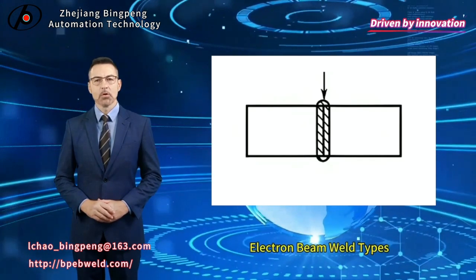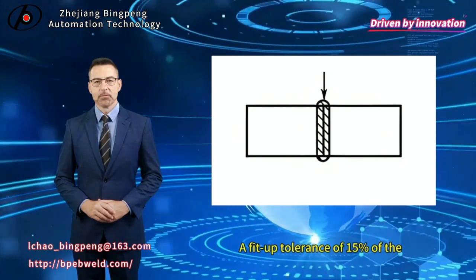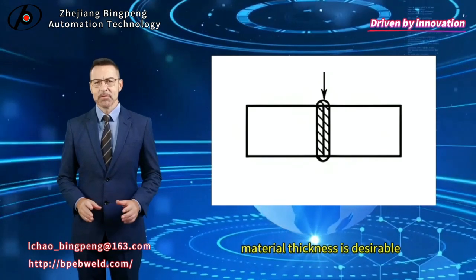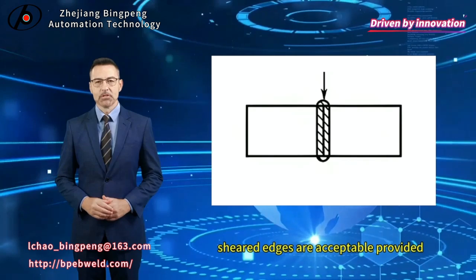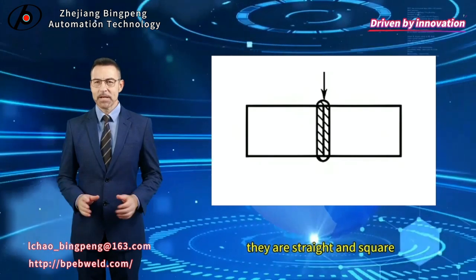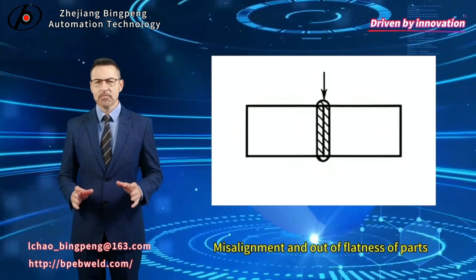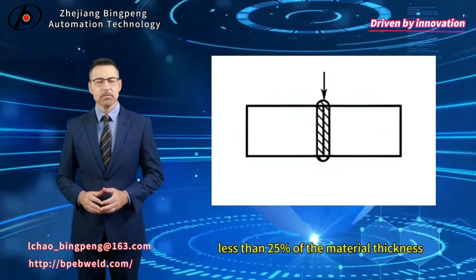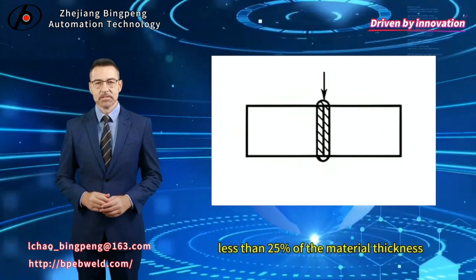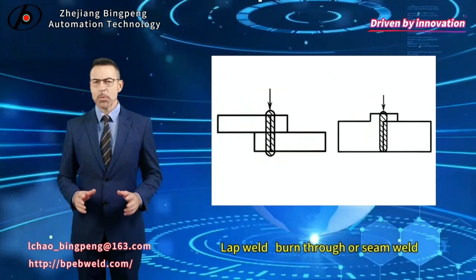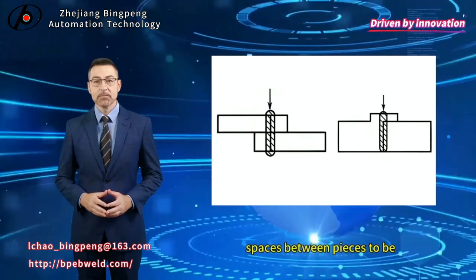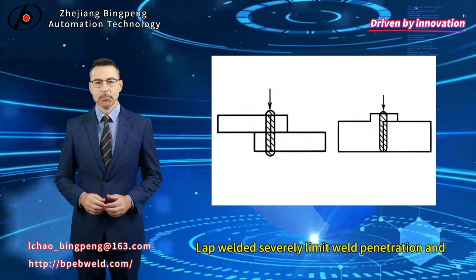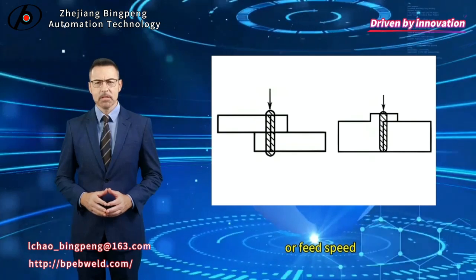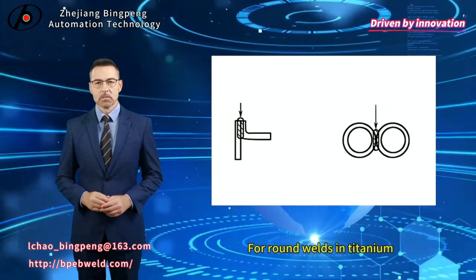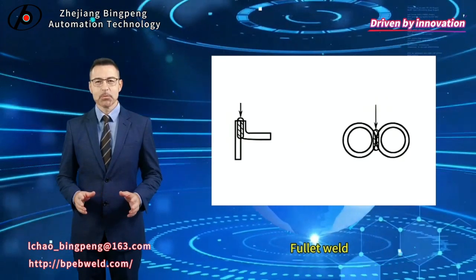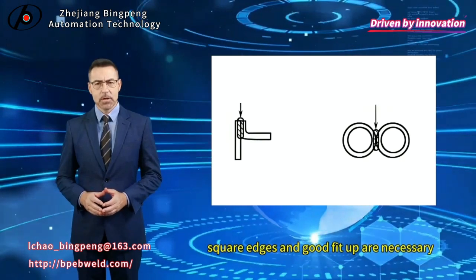Electron beam weld types. Butt weld. A fit-up tolerance of 15% of the material thickness is desirable. Sheared edges are acceptable provided they are straight and square. Misalignment and outer flatness of parts should be less than 25% of the material thickness. Lap weld, burn through or seam weld. Spaces between pieces to be lap welded severely limit weld penetration and/or feed speed. For round welds in titanium, no gap can be tolerated. Fillet weld: square edges and good fit-up are necessary.